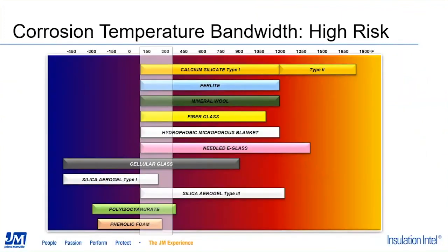So if we look at what we call the corrosion temperature bandwidth, what we're looking at here is a graphical representation of all of the products that are used on hot systems today. And we would consider this what we call high risk. So this is going to be a system that would be ambient up to 350 degrees. And when you have something operating in this range, you want to pay close attention to what's going on with the system, because you're at a pretty high risk of developing corrosion under insulation.